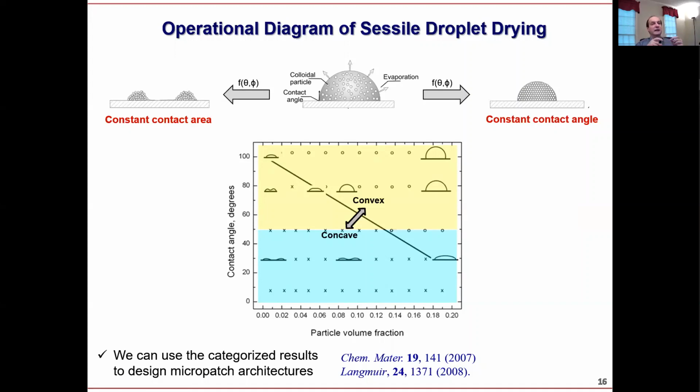but they cared a lot when those folks at the University of Chicago reported the coffee ring, which is essentially what happens if you have a droplet and you have organization of particles at the periphery of the drying droplet, right? So if you have a contact angle which is fixed in this case, so you have no slip of the contact line, the particles will be accumulated because the evaporation takes place here.